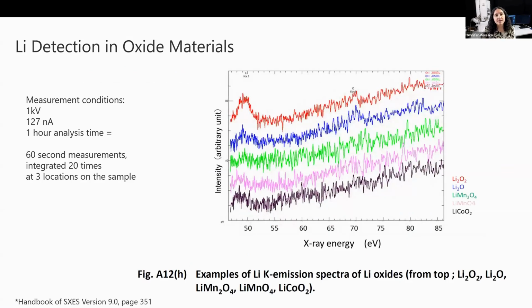And here you can see spectra from a selection of other lithium oxide materials. Since the emission is very weak, high probe currents and long measurement times of 1 hour per spectra were used. So even though the signal is weak, we can detect a slight lithium peak in these materials. Now, I also showed lithium cobalt oxide before and said it was not possible to see a couple slides ago. But in this case, it's a different sample of this material, and the measurement time is much longer with higher currents and lower kV.